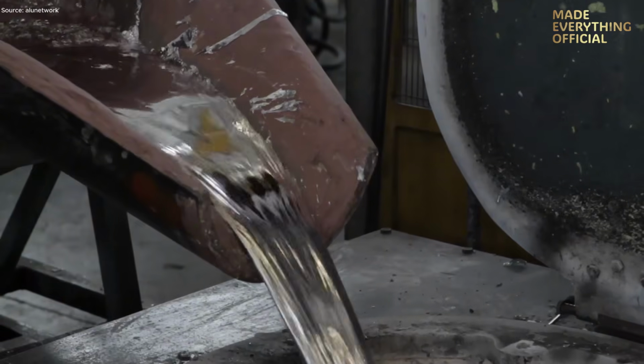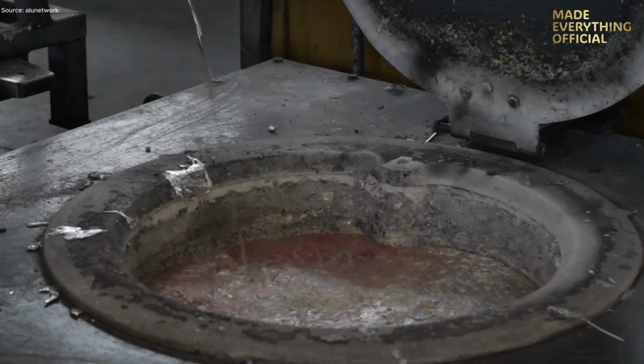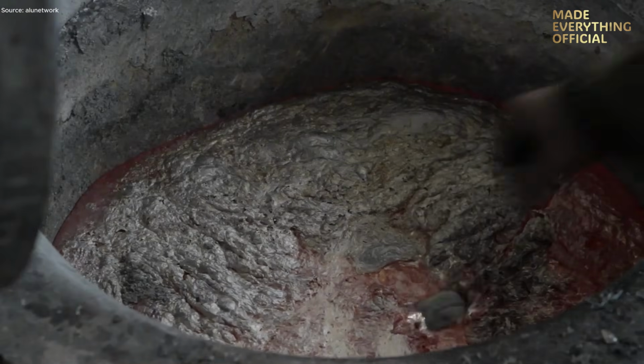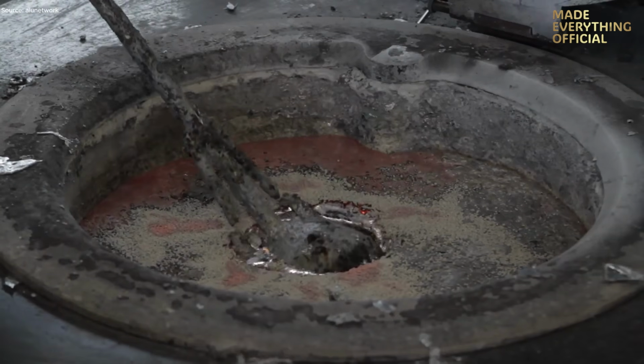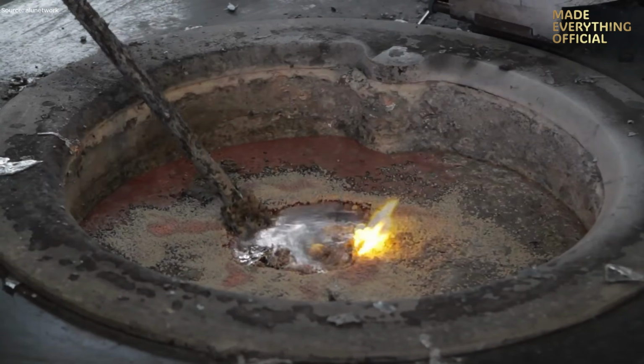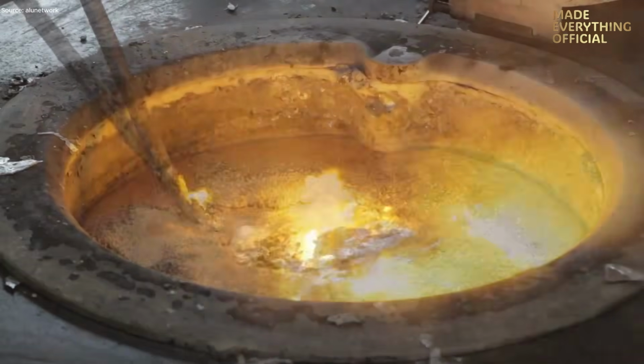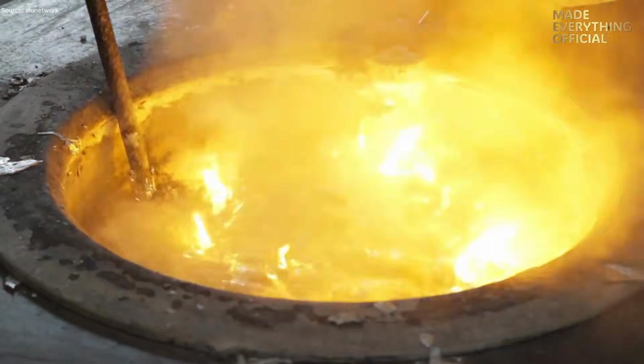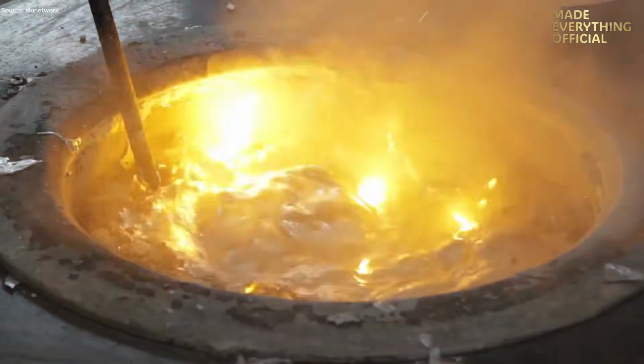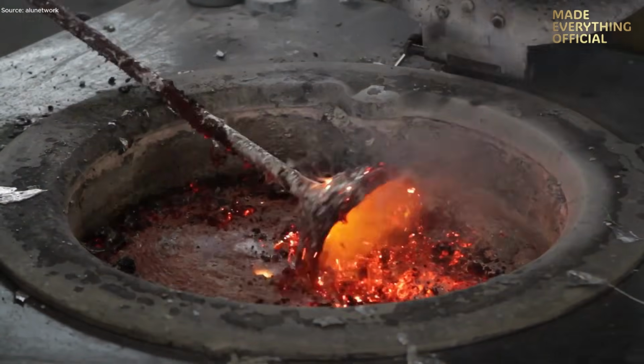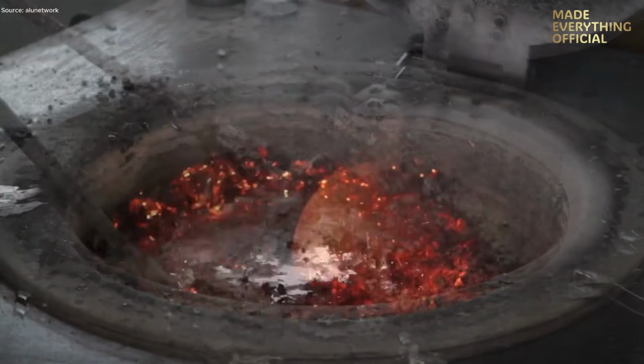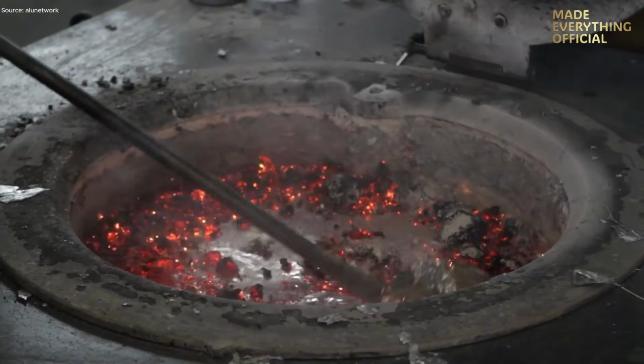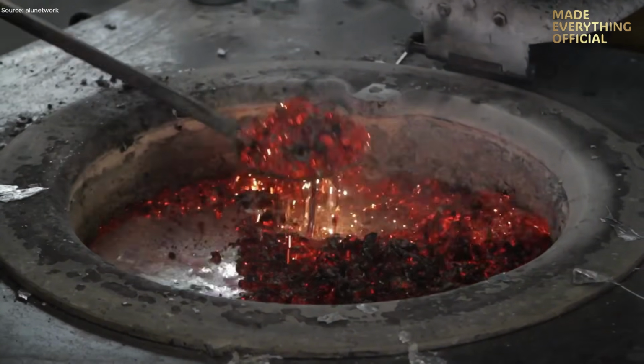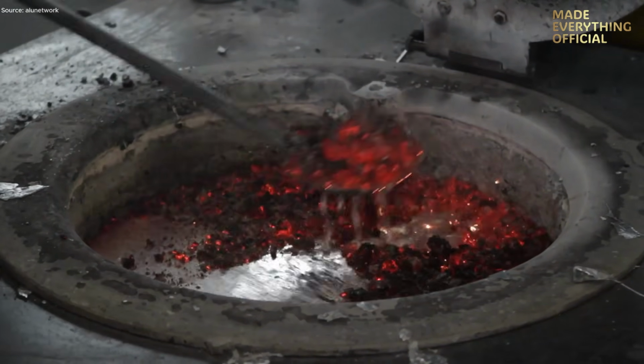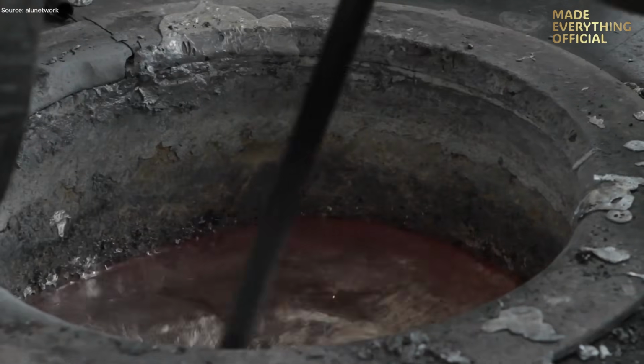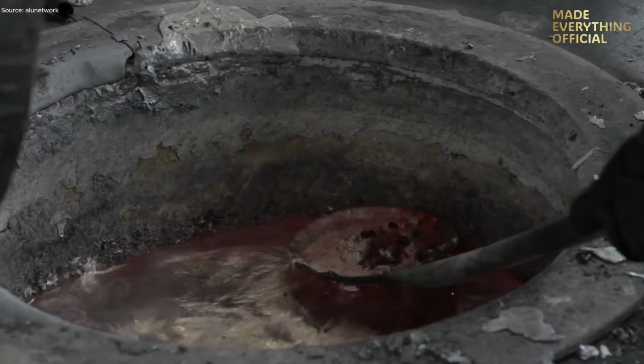Once the aluminum is fully molten, the melt undergoes an additional refining step. A small refining agent is introduced into the liquid metal and mechanically stirred. This treatment causes impurities and dissolved gases to rise to the surface as slag. Operators then carefully skim this layer away, cleaning the melt before casting. This step is essential for improving internal structure, reducing porosity, and ensuring consistent mechanical properties in the final parts.